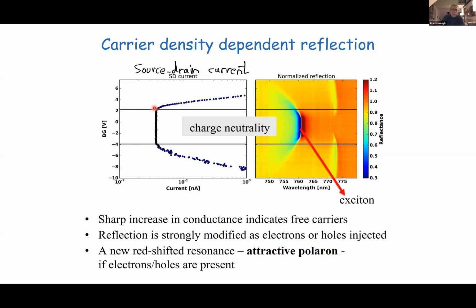What you see is that there is a certain gate voltage range where the current is vanishingly small, and then you can inject electrons and increase the conductivity, or inject holes and achieve the same. Now you can do optical measurements on the same device. When the system is neutral, in reflection or absorption measurements, you can think of it that way, there's a prominent exciton line. Even before the current turns on, it starts blue shifting, and then a new resonance appears on the low energy side that picks up sizable oscillator strength. It actually becomes stronger than the main exciton peak for densities of a few times 10 to the 12.